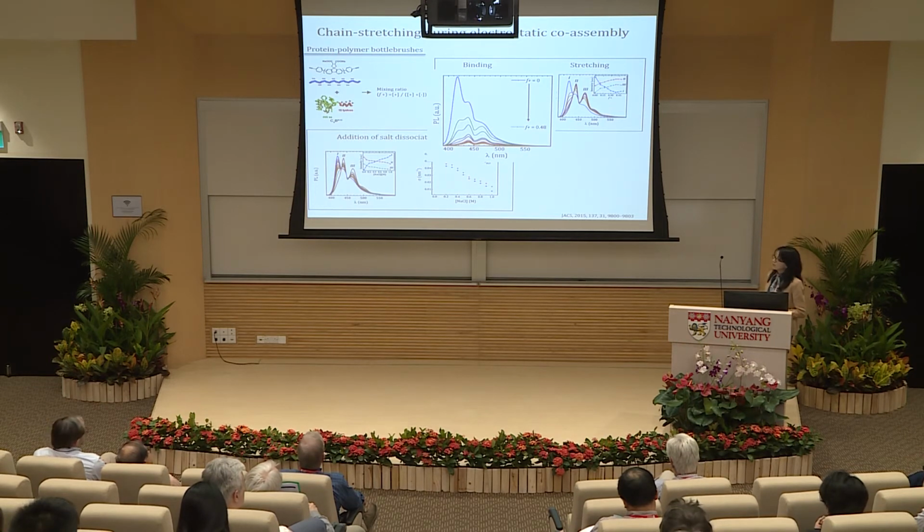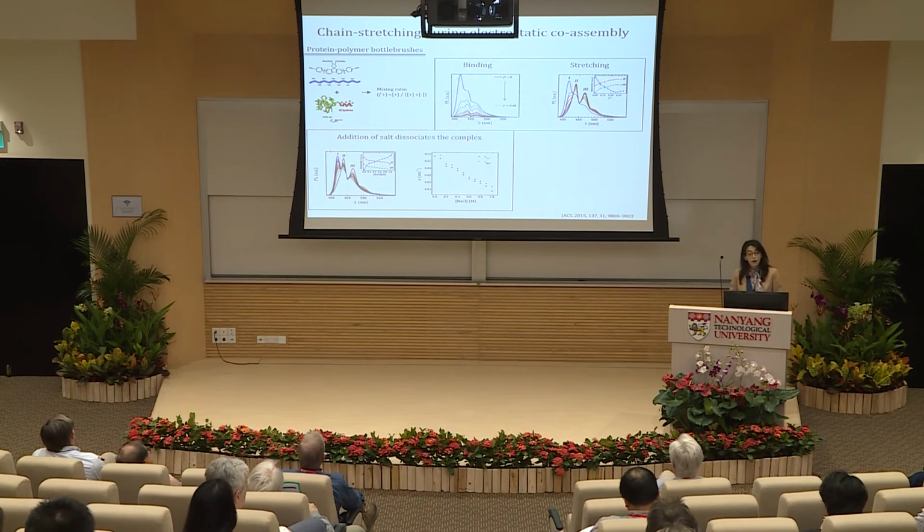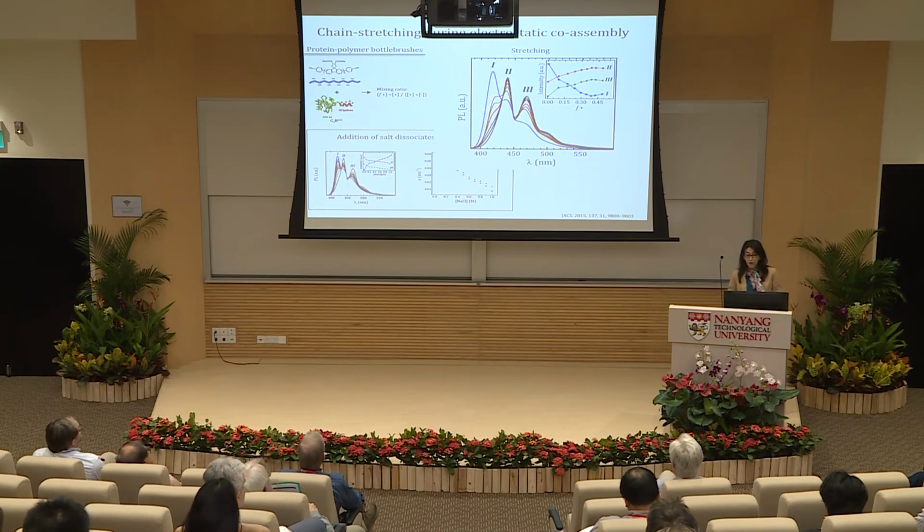So simply, by increasing the mixing ratio, adding more polypeptide into the system, we are quenching the fluorescence intensity which comes from the polyfluorene. So that is the number one confirmation that this system is complexing, and gradually binding on the conjugated polyelectrolyte. But a more striking piece of information comes from the fact that this polymer, as I told you, can transform from a regular phase to a beta phase.